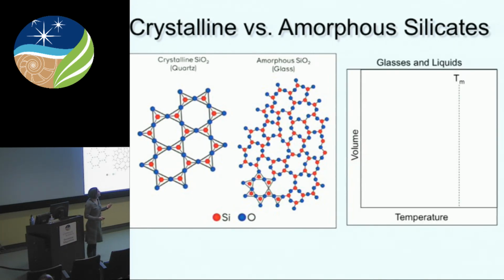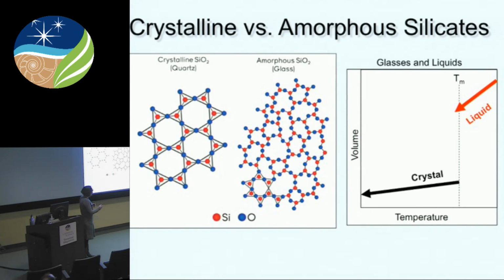And just because many of us don't work on glasses and liquids, I'm just going to briefly tell you the difference here. So when you cool a liquid, right, there's some temperature, the melting temperature, where you would predict that you would crystallize a material, right? So this is volume as a function of temperature, and here we have a liquid coming down. When it reaches the melting temperature, you have a large volume decrease because the atoms are able to rearrange themselves into a repeating structure. It's the lowest free-energy phase, and so you end up with a crystal that's down here.